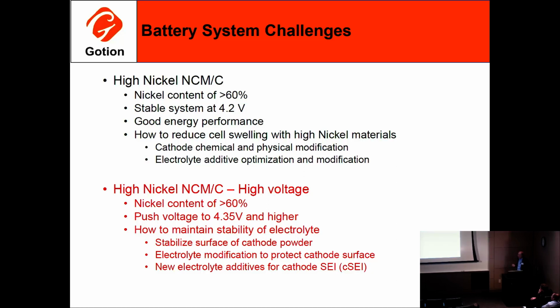The SEI on the anode, everyone pretty much knows about, is on graphite, and that's been around for a long time, and there's a lot of good solutions to that today. But as you try to keep the electrolyte out of the cathode pores and out of the catalytic activity of the nickel, you start to put coatings and things like that on the cathode side so that it protects it as well. An example of that is, and this is a different system, data from an LCO cathode system.